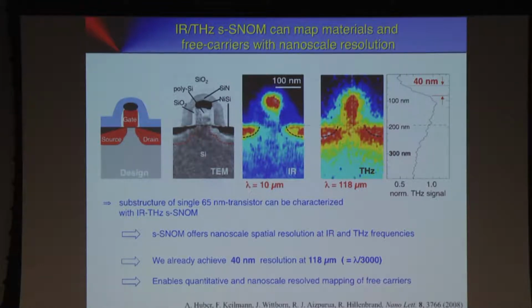Then we image that at 10 micrometer wavelengths, and we can very clearly see here these bright areas. This is the metal, because principally it functions very similar to a standard microscope. Metal is highly reflective, and for that reason, if you place the tip above a metal, we get a lot of backscattering from the tip. That's why the metal appears bright. So the lower the dielectric of the material onto which we place the tip, the less of this nanofocus is reflected and modifies the tip scattered light. And that's why these dielectrics here, like silicon or silicon oxide, appear dark here. So the contrast here resembles very much the contrast in a reflection type microscope.